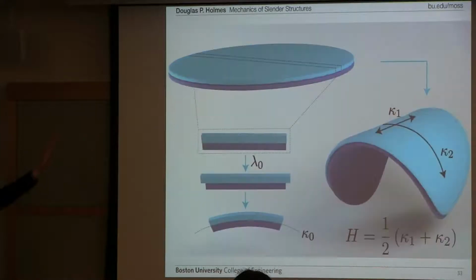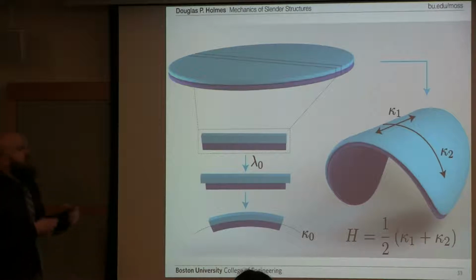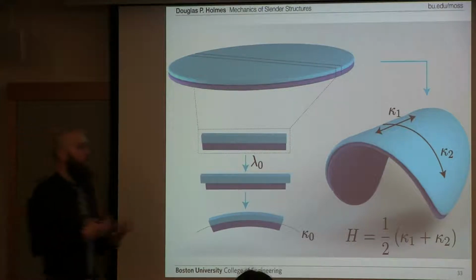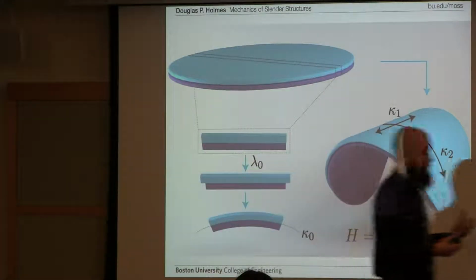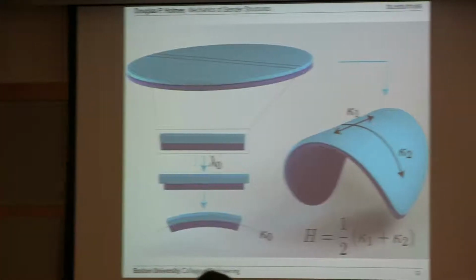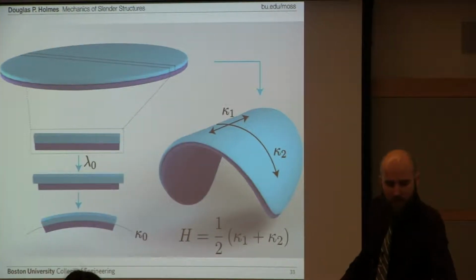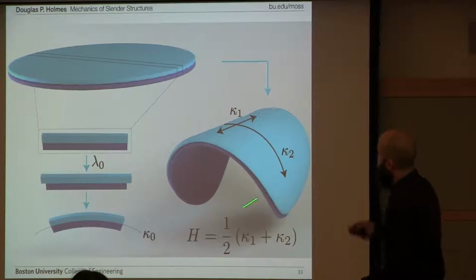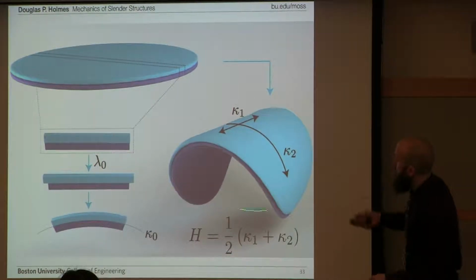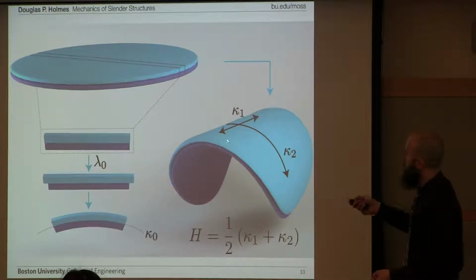And that old problem is the bilayer plate problem. So you take a plate that has a bilayer, the top layer is going to grow, the bottom layer is going to shrink, and we ask, what's the shape going to be? We try to grow this thing into a sphere. We know that it can't form a sphere, so we know that it's going to form some sort of cylindrical-like shape. We measure this shape by its mean curvature. So the mean curvature is the average of the curvature in this direction and the curvature in this direction.